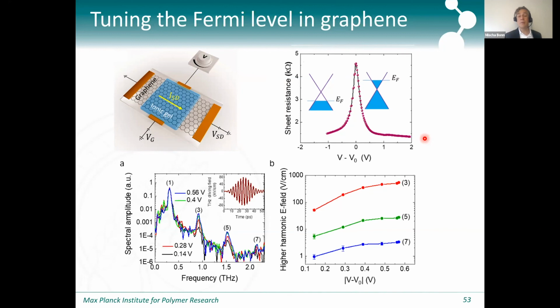The problem, or I think one of the drawbacks of terahertz, is that because the wavelength is so long, right? It's a sort of 300 micron or 100 micron wavelength. You cannot focus it very tightly. So for these 2D materials, you really need extended samples. If you're thinking about twisted bilayers, the correlation length of that twist is usually a lot shorter than 100 microns. And so that makes it difficult to use terahertz on those complex materials.